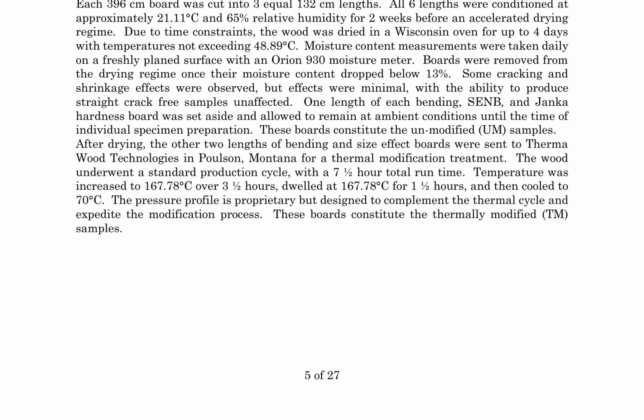The boards were then split into 2 groups: unmodified samples, which remained at ambient conditions, and thermally modified TM samples, which underwent a standard production cycle at Therma Wood Technologies. The thermal modification treatment involved a 7.5 hour total run time, with a temperature increase to 167.78 degrees Celsius over 3.5 hours, a 1.5 hour dwell at 167.78 degrees Celsius, and subsequent cooling to 70 degrees Celsius. A proprietary pressure profile complemented the thermal cycle to expedite the modification process.